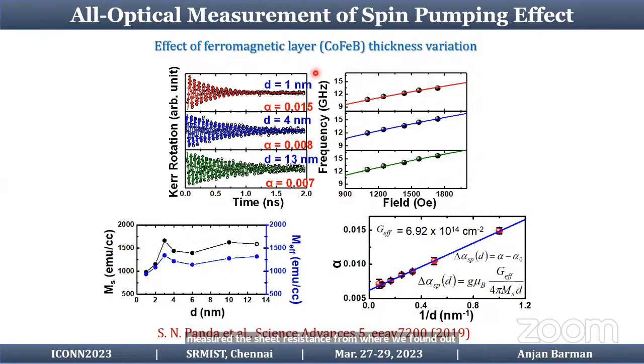This is the time resolved experiment, and you can see the damping as a function of different values of ferromagnetic layer thickness. We plotted alpha as a function of 1 over d, because alpha changes as 1 over d, and from here we can find all these parameters. We are able to find the effective spin mixing conductance, because it shows a pure linear dependence with 1 over d, which is 6.92 times 10 to the 14 per centimeter square.